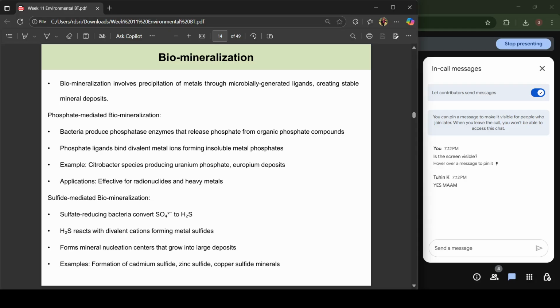And when we talk about biomineralization in the context of metals, it involves the precipitation of metals through microbially generated ligands, creating stable mineral deposits. For example, you have phosphate mediated biomineralization where bacteria produce phosphatase enzymes. This is going to release the phosphate from organic phosphate compounds, and the phosphate ligand thus generated binds with the divalent metal ions and forms an insoluble metal phosphate complex. So you can find this in Citrobacter species, which produce uranium phosphate and europium deposits, and this can generally be used in remediation of radionuclides and heavy metals.